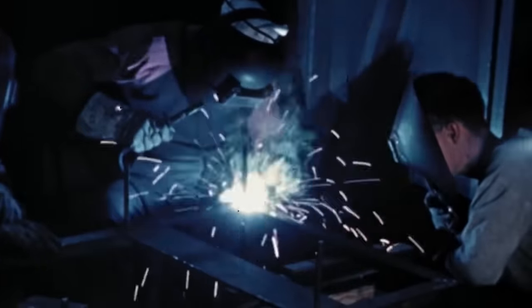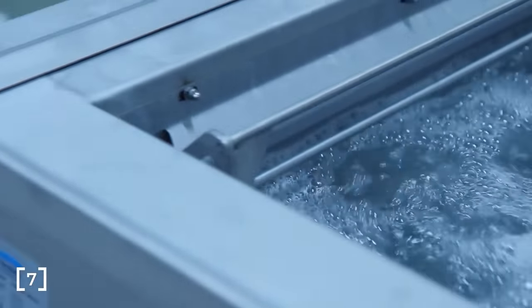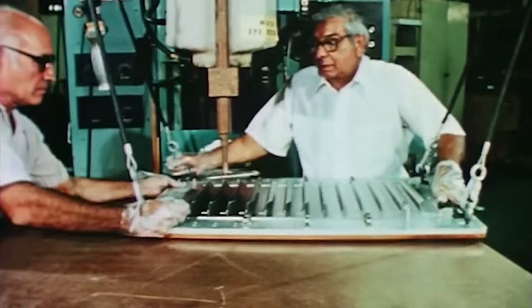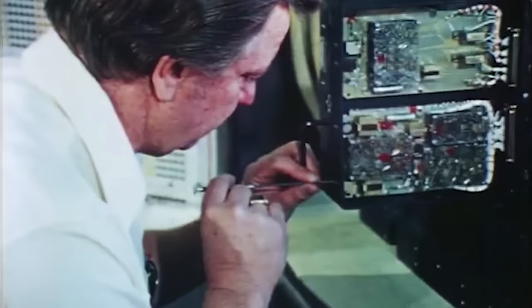This process results in an incredibly expensive material that becomes even more expensive due to the difficulty engineers found when forming it into its final shape. The engineers of the SR-71 were among the first people in history to make real use of the material, and in that process they ended up throwing away a lot of material. They discovered that spot-welded parts made in summer were failing very early in their life, but those welded in winter were fine. They eventually tracked the problem to the Burbank Water Treatment Facility adding chlorine to the water in summer to prevent algae blooms — chlorine reacts with titanium — so they began using distilled water. They also discovered that cadmium-plated tools were leaving trace cadmium on the bolts, causing galvanic corrosion and bolt failure, leading to all cadmium tools being removed from the workshop.